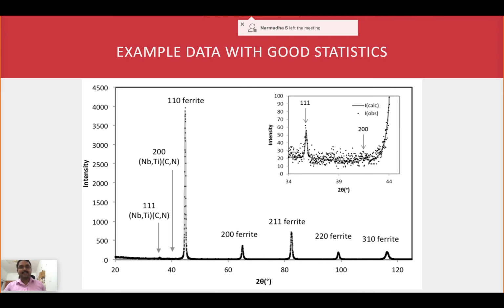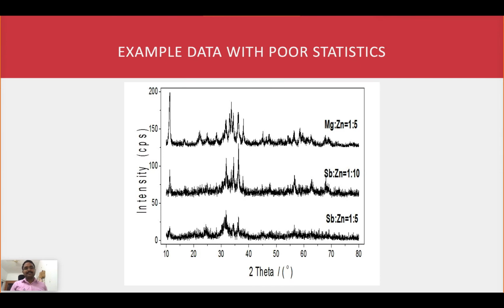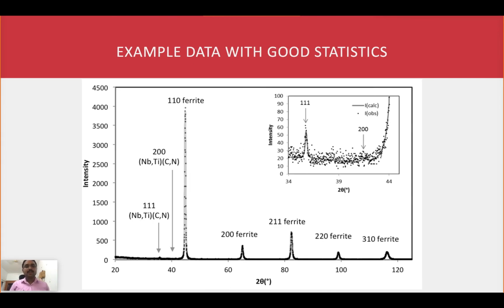Now we are going to go for data with good statistics. You can see good statistics means even the smallest peak is almost visible. The 100% peak is very clear, and we can see a large difference in the values between the highest peak and the background values. But still, if you zoom in, you can see small peaks are also available. So I can give an example like a good statistics, not better, good statistics. If you are able to distinguish your diffractogram, 2 theta values versus intensity graph like this, you can go for better analysis. You should have some knowledge of these things. So you should now be able to understand what is poor statistics, better statistics, and good statistics.